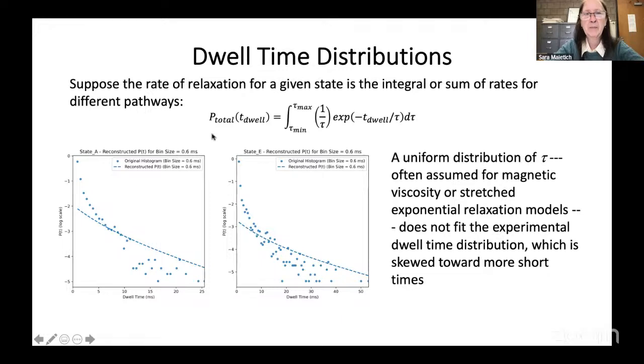One way to imagine this is if you have a distribution of dwell times that gives you a stretch exponential-like behavior, that you could have a more physics-based model if you just integrate the contributions for different relaxation times. But that requires that you have some sort of assumption about what the distribution of relaxation times would be. This is going to be something that we can calculate with Mumax 3 for a spin ice. We're in the process of doing that now, but we're also in the process of fitting the data.